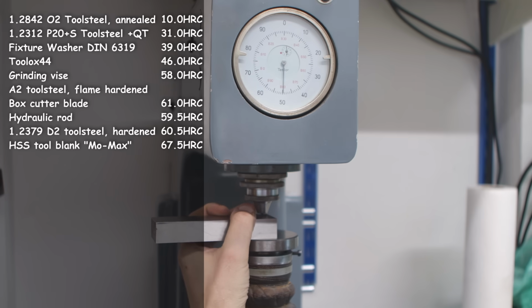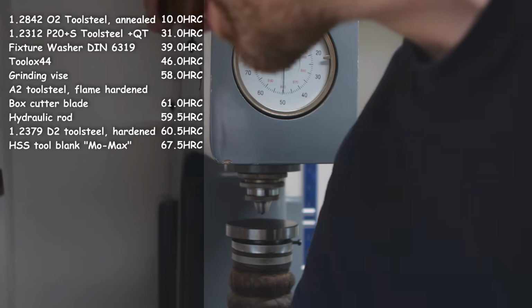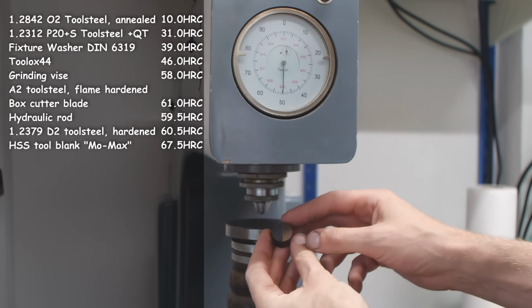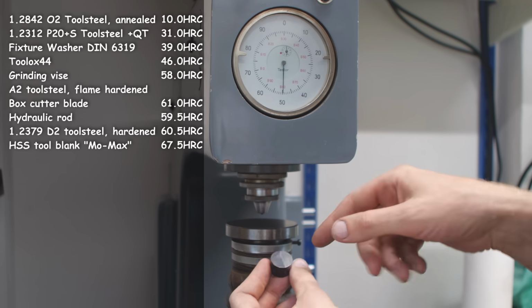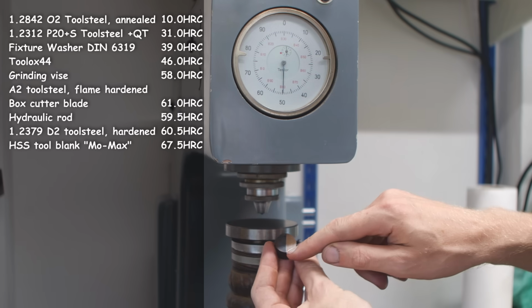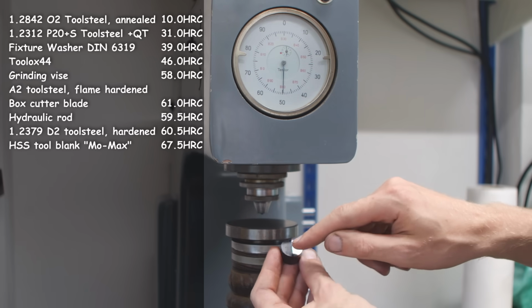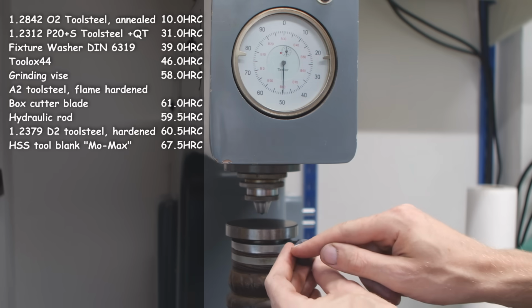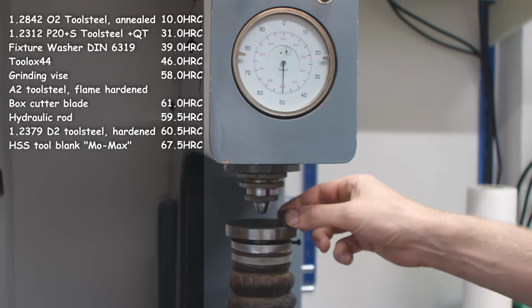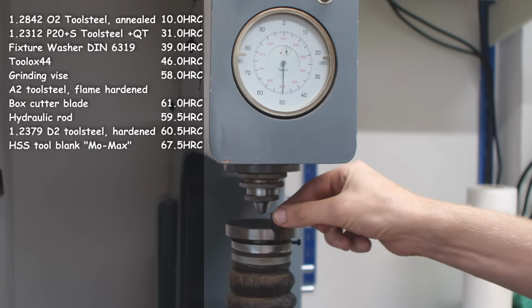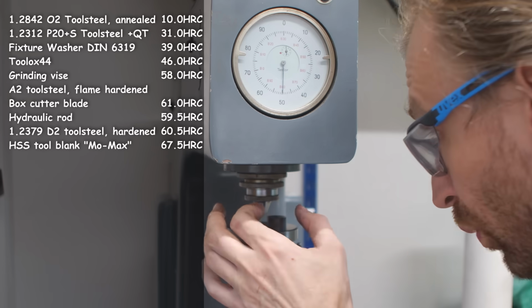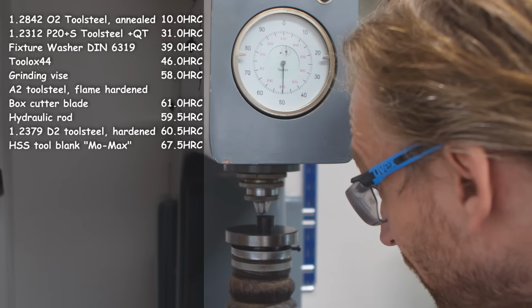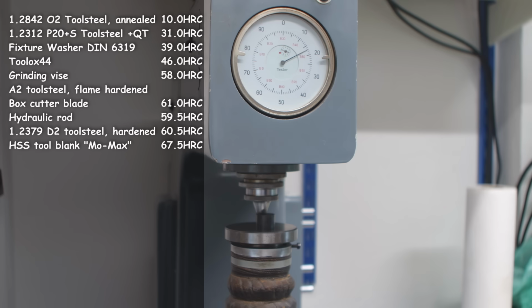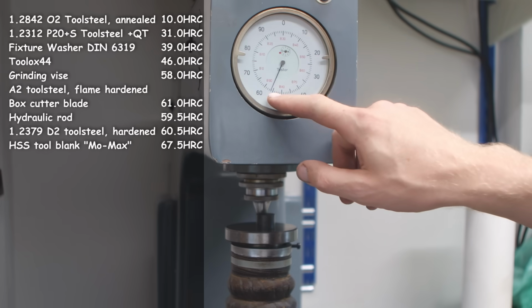This is just soft. Okay, and the last one that I saved is the piece of A2 tool steel. A2 is the air hardening tool steel, so I just torch hardened it. And I surface ground 20 microns off one side to get rid of the scaling from hardening, and I left the scale on the other side for a reason. The back side is just sanded on the sanding plate. So first we check on the scaling. The heat treat is not brilliant on this, but we should get a result. So we get 56 on the scaling.